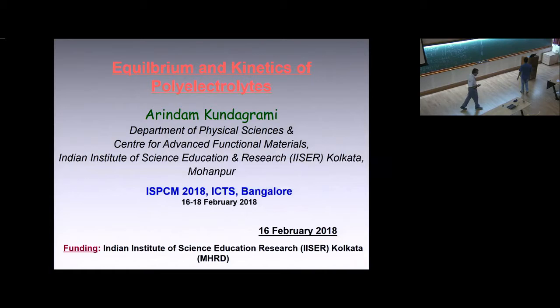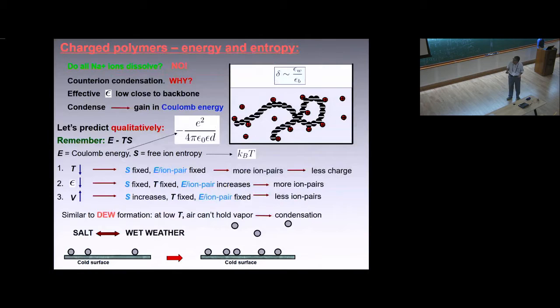Okay, thank the organizers, and I'll be talking about work where the basic principle being followed is the competition between electrostatic energy and free-ion entropy. It's whether the counter ion will condense on a charged monomer or be free. If free it enjoys entropy, if condensed it enjoys electrostatic energy with negative sign. The dielectric constant, depending on solvent polarity, plays a major role in determining the equilibrium fraction of counter ions. With more salt you'll have more condensation.